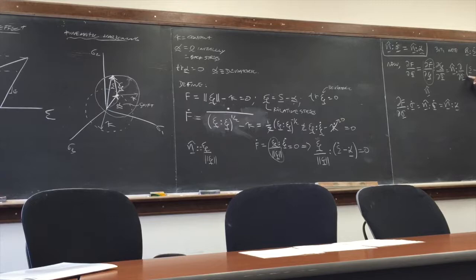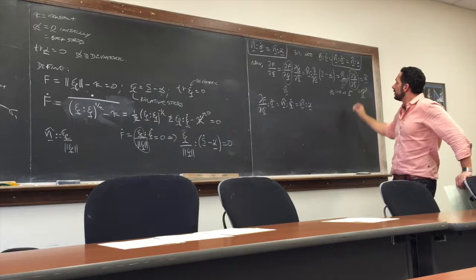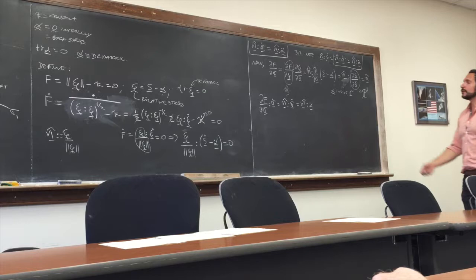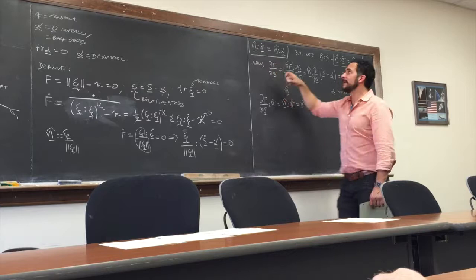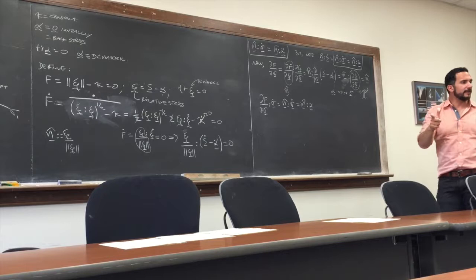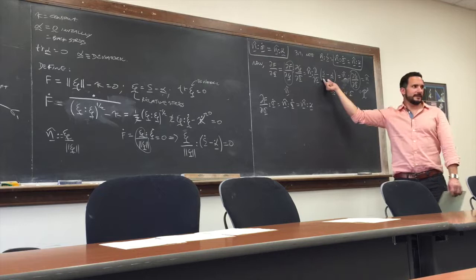So that has to do with the derivative of alpha with respect to sigma being zero. And that has to do with the fact that alpha is independent of sigma. So whatever sigma changes you have, it has nothing to do with alpha in general. Now, you could argue, well, you just told us that alpha has to evolve more or less with respect to s. But that doesn't make it directly dependent on sigma, because sigma has 2 degrees of freedom. One is in the S direction, and the other one is in the hydrostatic direction. So in general, a change in sigma doesn't imply a change in alpha. That's why that derivative is zero. Now, a change in sigma is always related to a change in S.